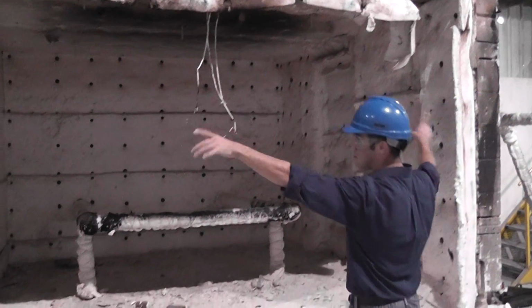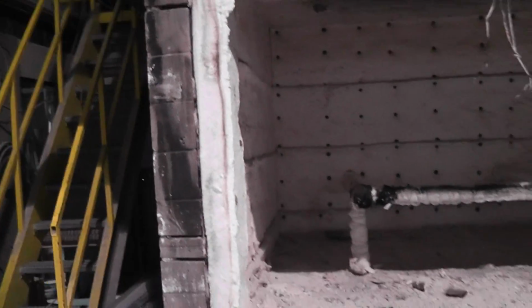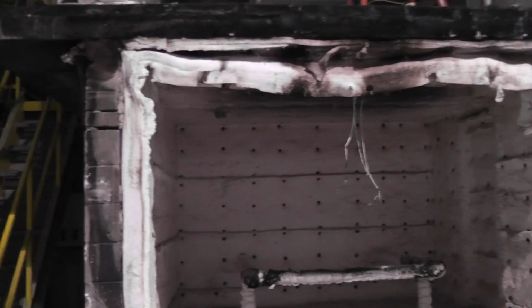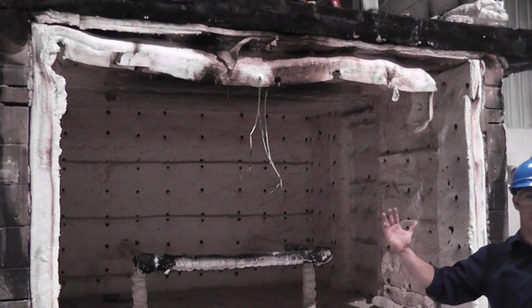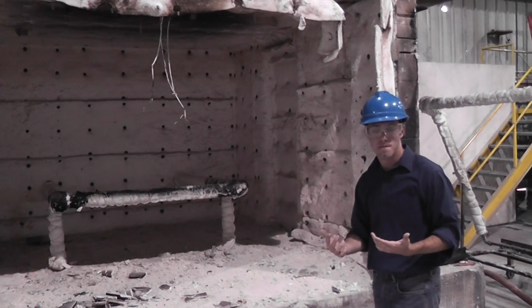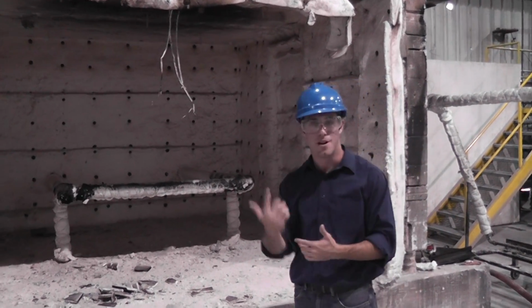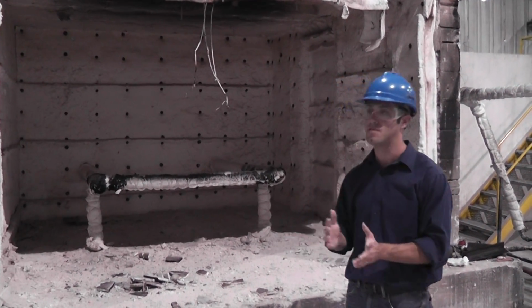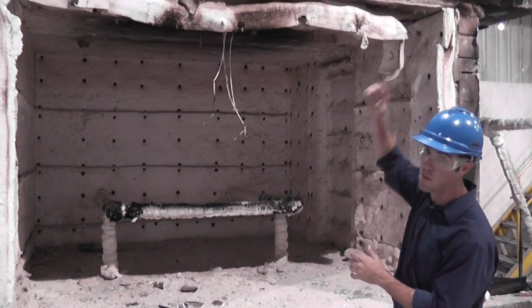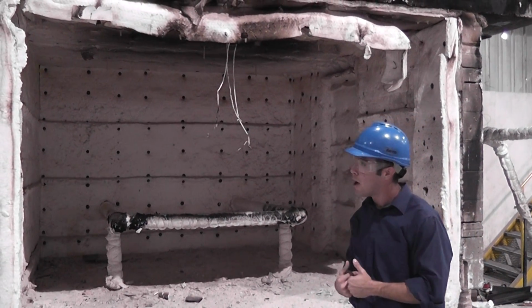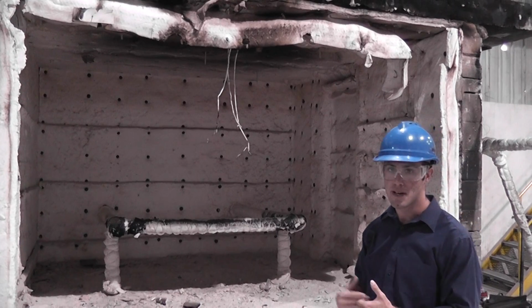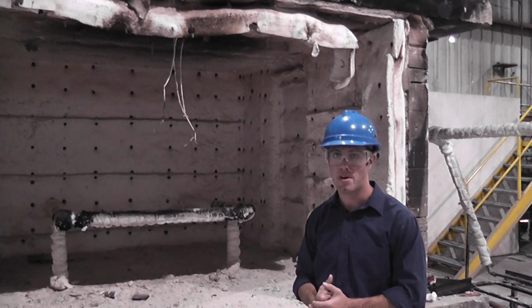Also, lateral flame spread, as a failure criteria, it can't spread 5 feet to either side of the window, but flame tends to travel upwards, so you don't see that very commonly. The typical mode of failure would be straight up the wall on the exterior face. So yeah, that kind of covers this apparatus.